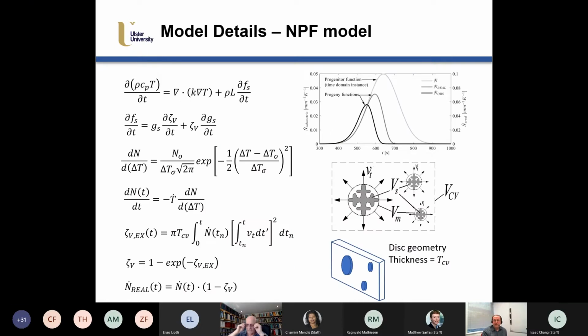Just some of the model details. It's a continuum model. The biggest difference here is that we had to move away from spherical growth, so spherical representative element volumes, to disc-like geometry to account for the thin samples. Now, there's no stereology issue with this because it's a thin sample. So the stereology problems and transmission all go away because of the very, very thin sample. So that was one aspect that was simpler for us in this case.